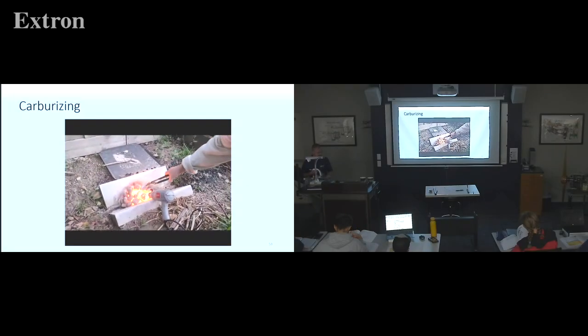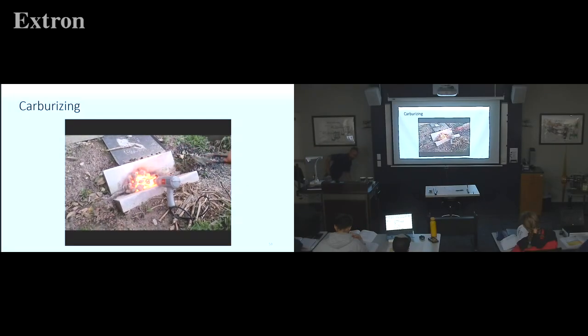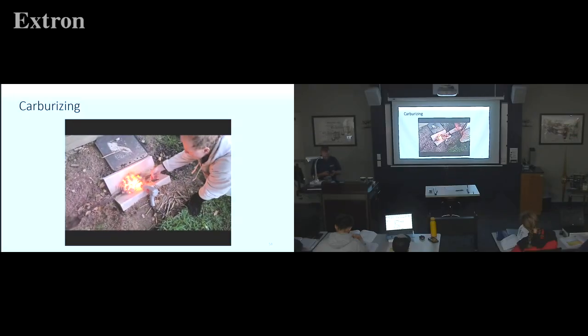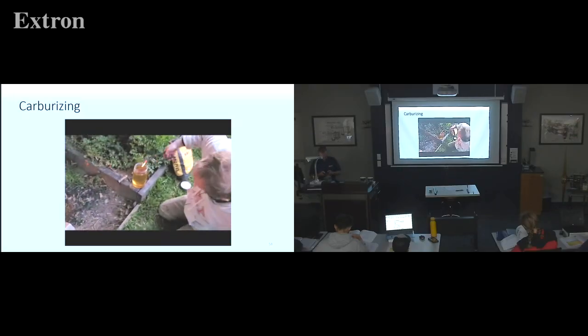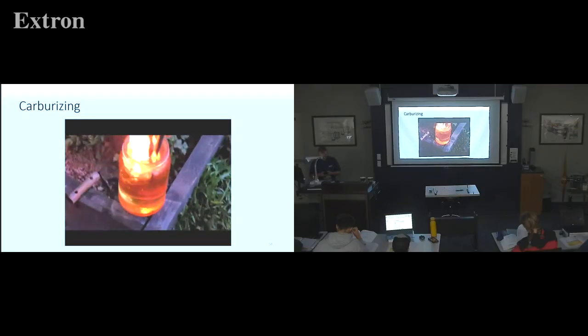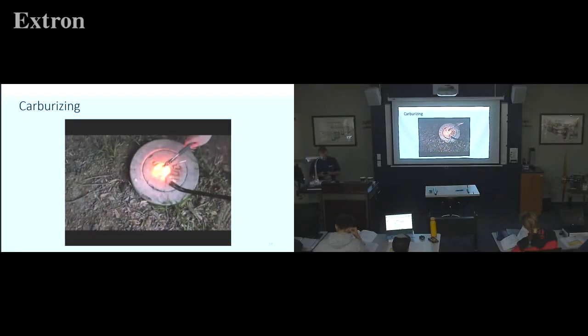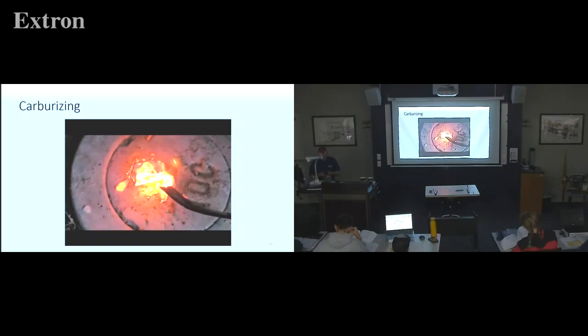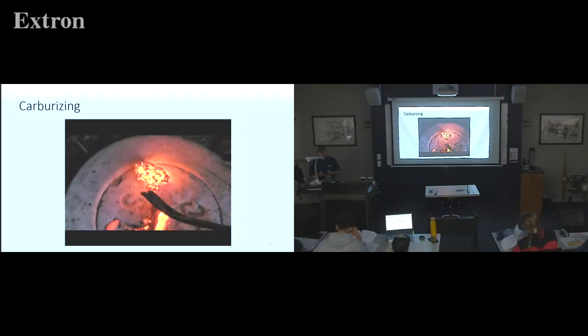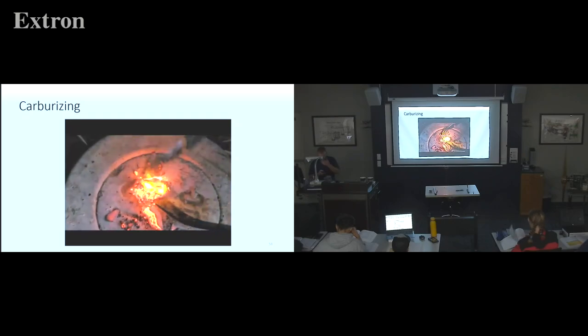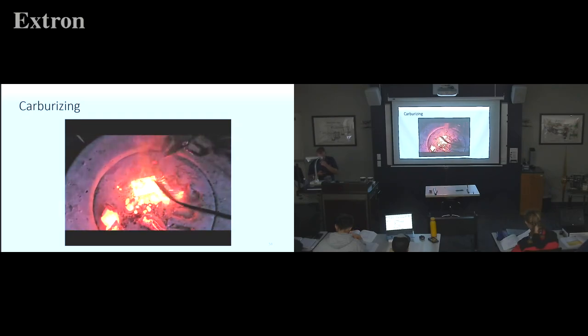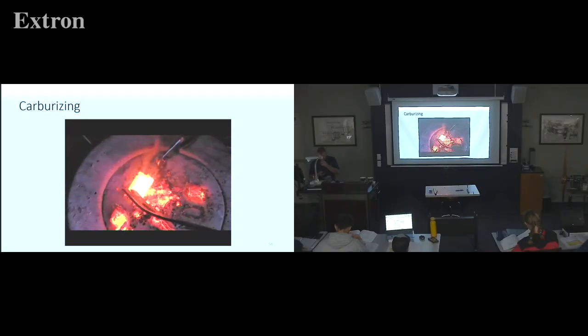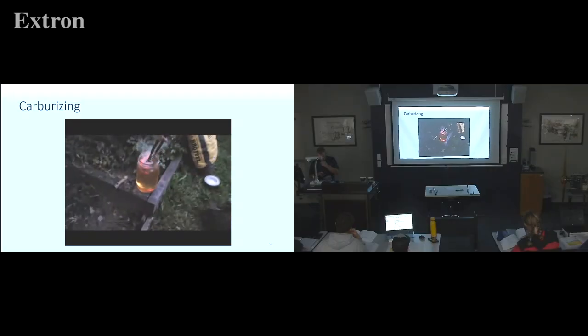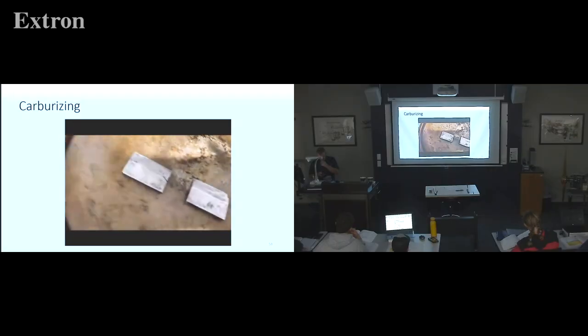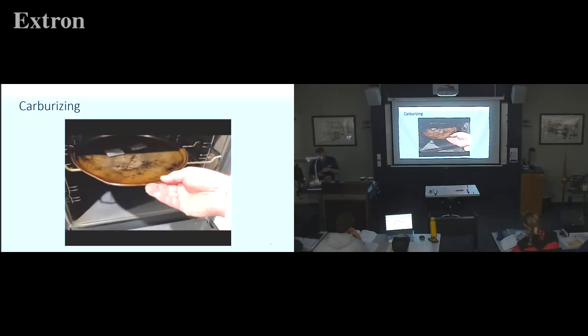While my carbon wrapped sample was cooking, I heated up my control piece in the forge and then quenched it in the oil, much like you would heat treat high carbon steel. This was to ensure that the only difference between the two was the carbon treatment process. After around 2 hours, I took out the clay and carbon wrapped sample. On a heat-proof surface, I carefully broke it open. The steel inside looked like it had been heating up very well, and hopefully therefore had been absorbing carbon from the charcoal, salt and flour mixture wrapped around it. Then I quenched it in oil, just like with the non-carbon wrapped sample. After they had cooled down, I tempered them in the oven on an old pizza tray for an hour at 200 degrees.